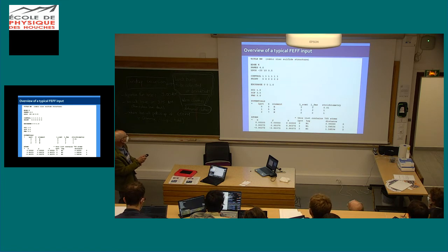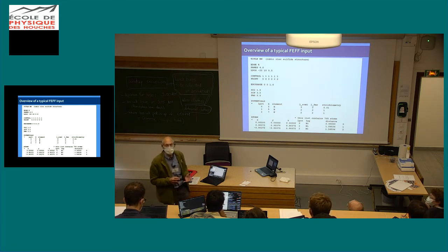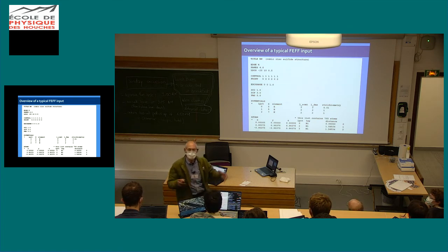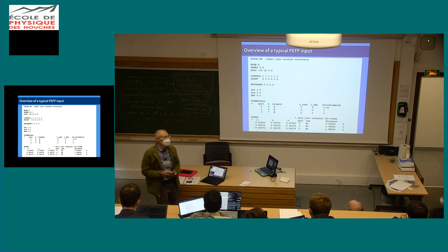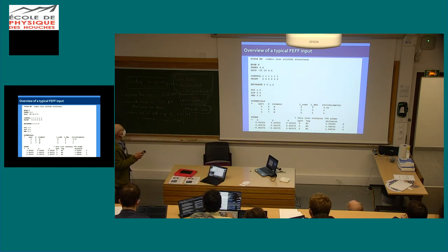Okay, this is a radius for the self-consistent calculation. For the self-consistent convergence, you only need about 50 atoms. Somehow you don't need the whole cluster because going out to 150 doesn't really change the densities that much. For the full multiple scattering, though, you go to a bigger cluster. This is typically 150 atoms.